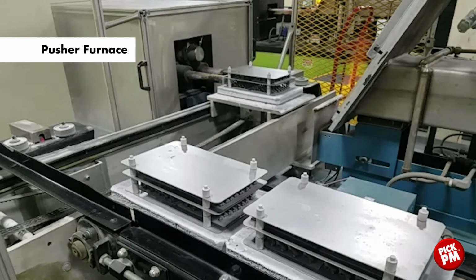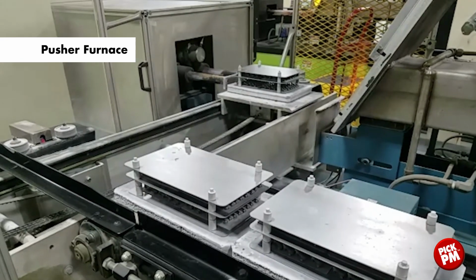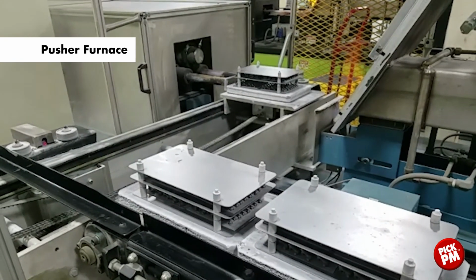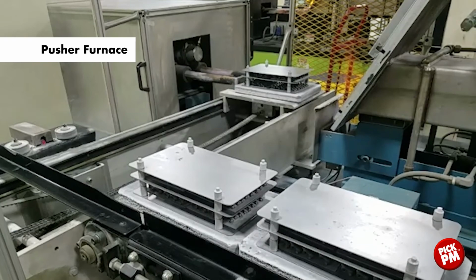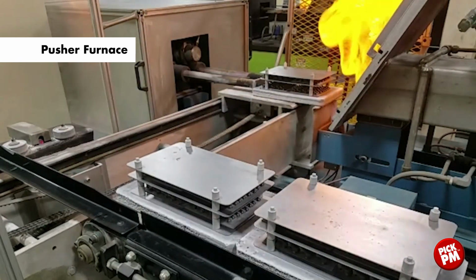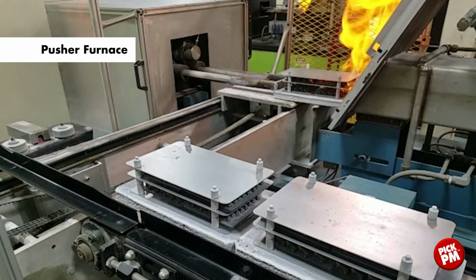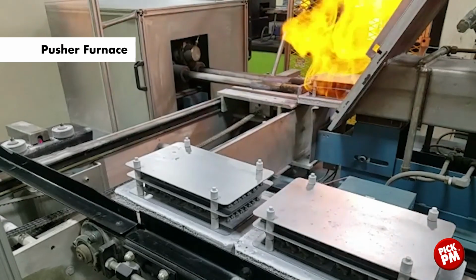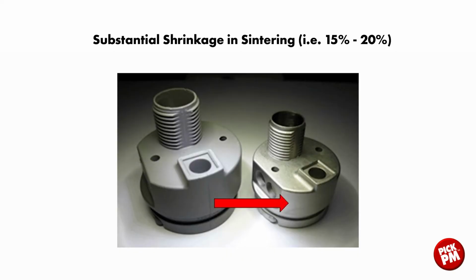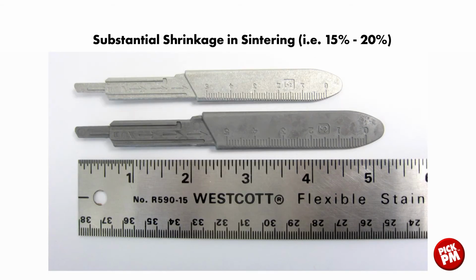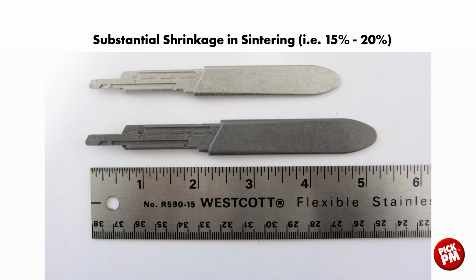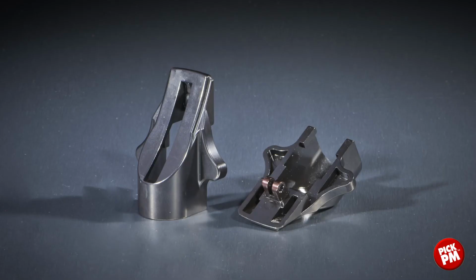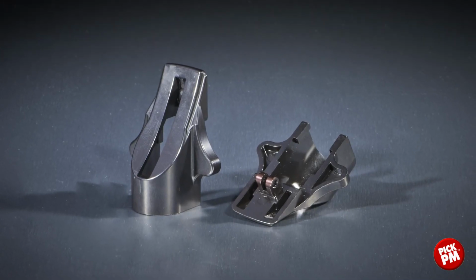After debinding, components are then sintered either in a pusher-type continuous sintering furnace or in a batch-type sintering furnace at elevated temperatures, either in vacuum or protective atmosphere. As you can see, in metal injection molded components, we oftentimes see as much as 15 to 20% shrinkage after the sintering process.